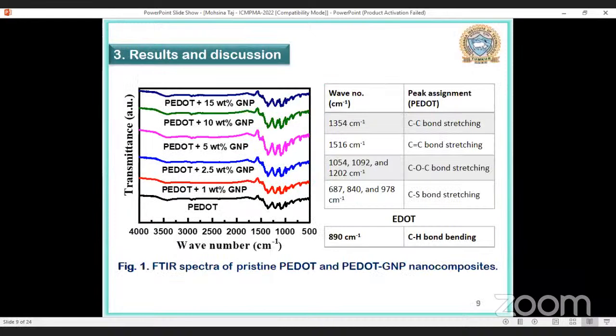We have studied the Fourier transform infrared spectra of the synthesized nanocomposite in the 500 to 4000 wave number range. In case of pure PEDOT and nanocomposites, there is a peak around 890 per centimeter in case of monomer EDOT, that is due to CH bond bending. This peak has disappeared in case of pure PEDOT and also nanocomposites, indicating the successful formation of polymer. Also the characteristic peaks of PEDOT were observed in the composites, but with a slight shift in the peaks, indicating the strong cooperative interaction between the polymer and the graphene nanoplatelets.